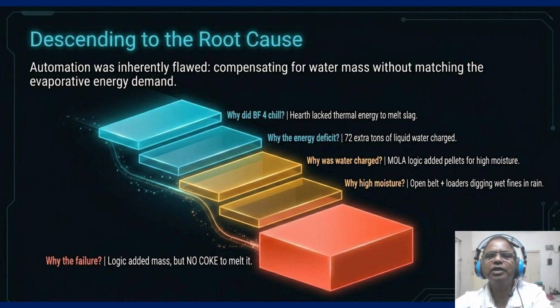Why was the water charged? Because the model logic added mass for high moisture. Why was the moisture high? Because we had an open belt and loaders digging wet fines in the rain. The ultimate failure, the red block at the bottom, was that our logic added mass but provided no coke to melt it. The so what factor is that our automation was inherently flawed. It understood mass but ignored evaporative energy demand. A senior engineer doesn't just fix the gauge, they fix the logic that misinterpreted the gauge.